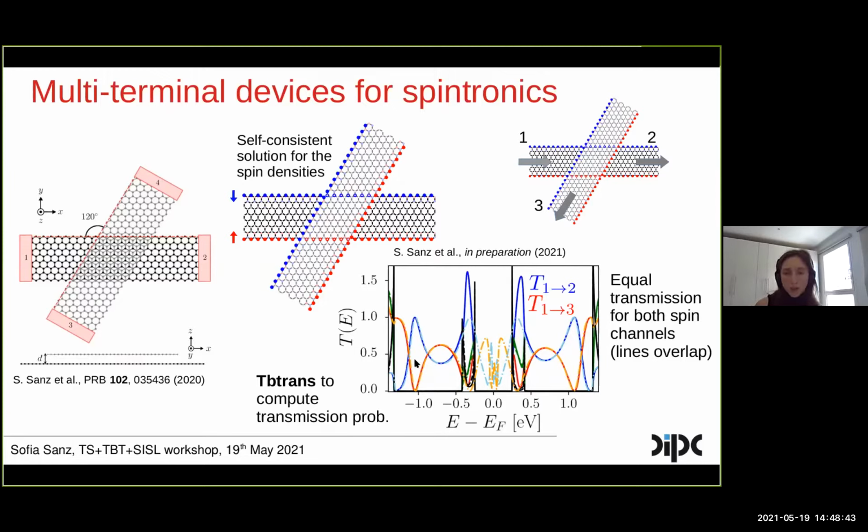So we can observe 2 things here. On one side, the beam splitting effect survives the presence of Coulomb repulsions. And on the other hand, the only thing that seems to be different from the unpolarized case when including electron interactions is that we now observe the band gap opening, the correlation gap opening that corresponds to the band structure of the polarized zigzag graphene nanoribbon.